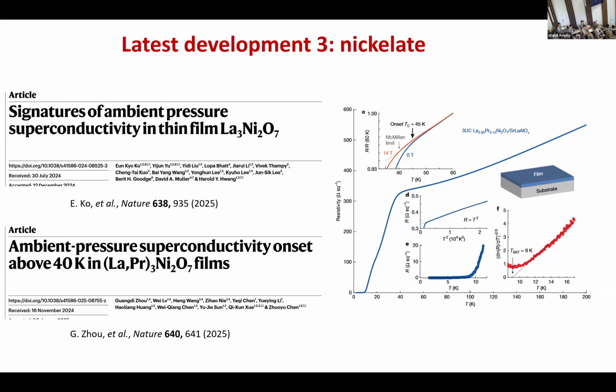Just because I don't remember this paper exactly, my memory is that superconductivity in nickelate was happening only when it's really thin. Is this film a bulk with pressure, or is it also a film? Oh, this is just thin film. Without pressure, still a thin film. Okay, but it's still not superconducting in bulk, even with pressure, right? So this 3-2-7 single crystal under pressure is a superconductor, and then they grow thin films in the same structure, and then they can have the superconductivity.